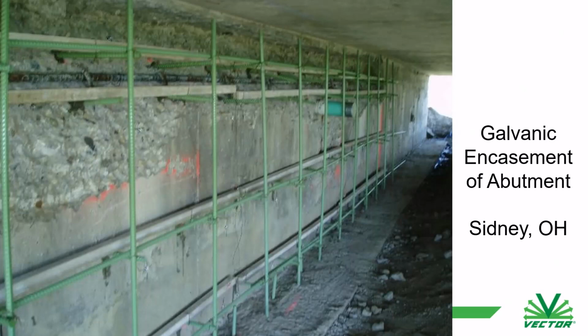And then this is showing the galvanic encasement being installed. So you see these tan long strips. These are distributed anodes made out of zinc. They're alkali activated, based on the same technology we've been using for 20 years. And you see dowels into the facing, new anodes going across.